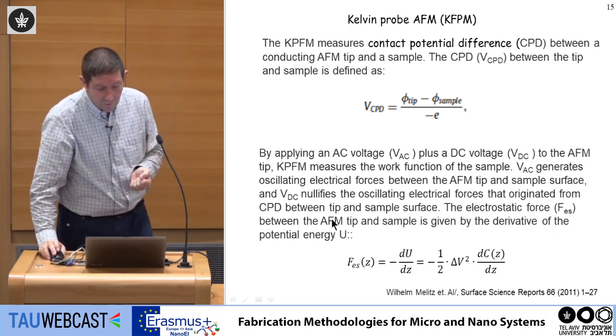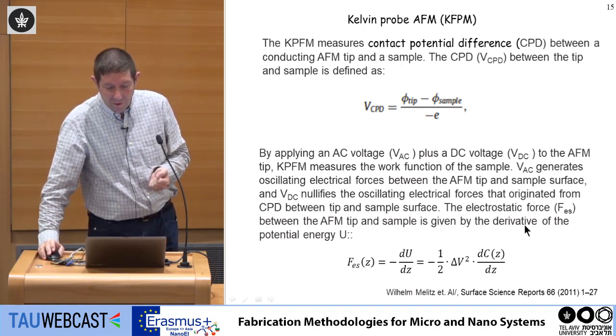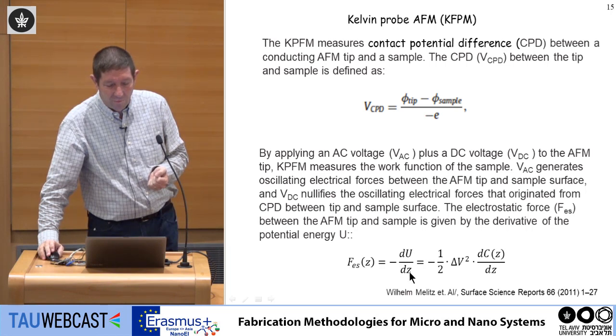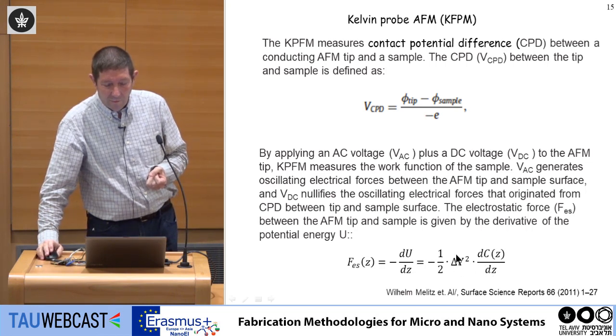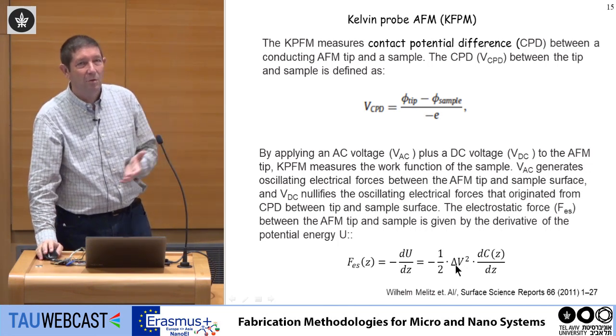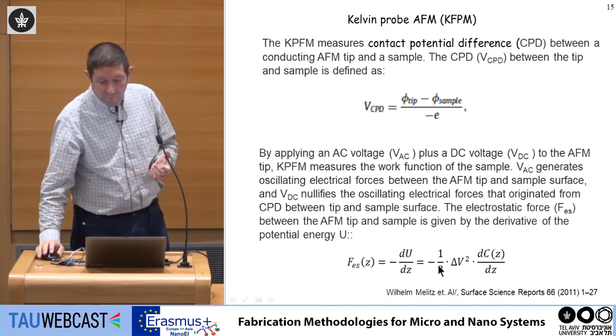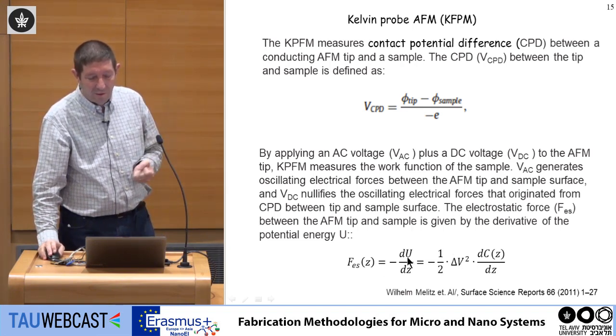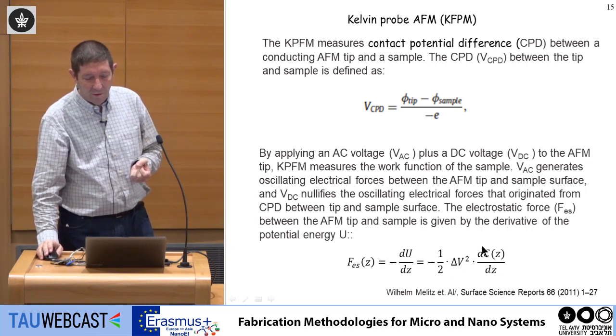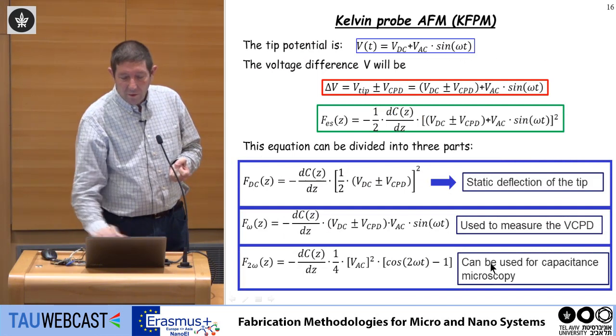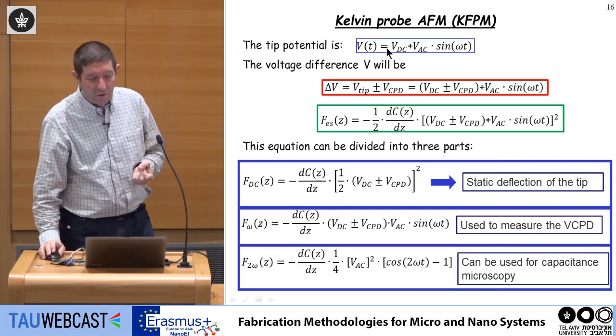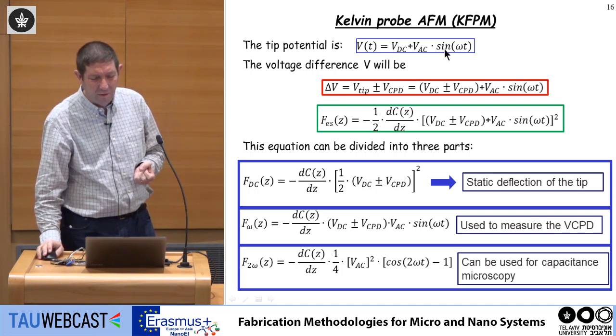The electrostatic force between the AFM tip and the sample is given by the derivative of the potential. We know that force is minus d potential over dz. Potential is half C delta V squared, so I get this. Now remember, this is an approximation; I neglect second-order effects. So using this approximation, if the tip potential is VDC plus VAC times sine omega t, then delta V is VDC plus VAC sine omega t minus VCPD. Then I calculate the force: half dC over dz times this term.